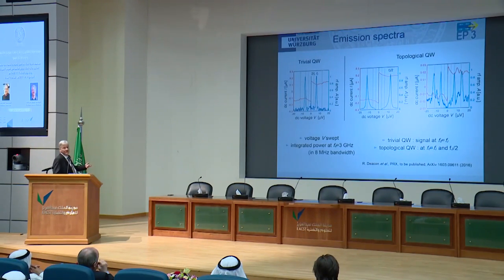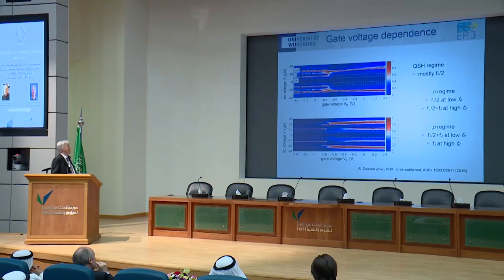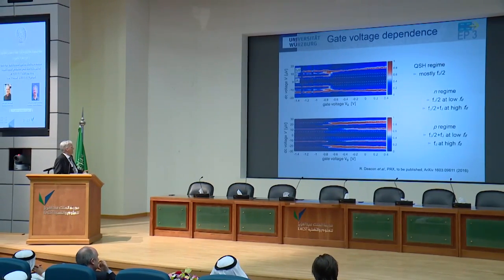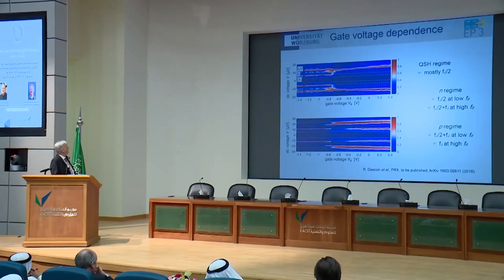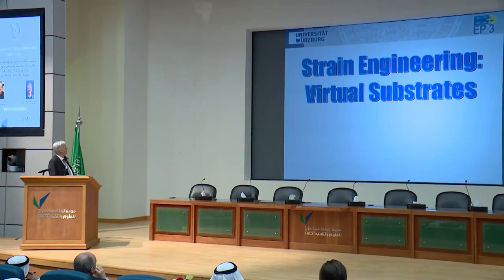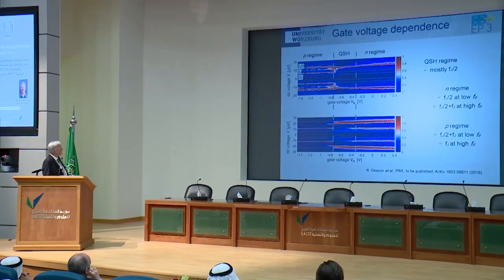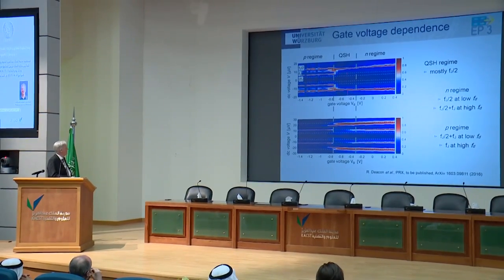And if we have this trivial quantum well, a narrow one, which is a test sample or a way to make sure that we measure the right thing, we only see the fundamental Josephson frequency. So this is a very straightforward to interpret experiment. The only way you can interpret this is that you have this zero mode present in your sample. Well, this is basically showing that it's not always there, not only there, if the gate voltage is in a quantum spin Hall regime.